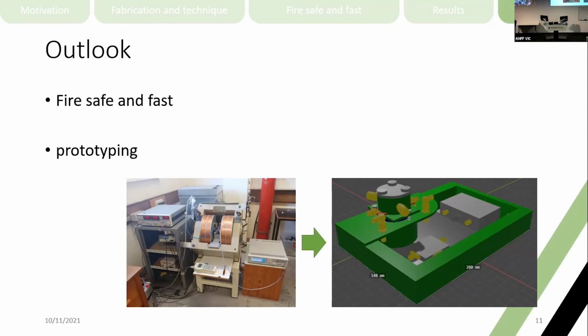Really interesting presentation. And I actually was wondering if you have already tested the hydrogen sensor under a bit more challenging conditions, in air or against potential interfering gases that could give a similar response to what you see for hydrogen. No, we haven't gone too much into that. So we tested our sensor for the response of hydrogen in dry air compared to nitrogen. You don't want to go too high there because it becomes quite dangerous or possibly explosive, of course. Typically, our sensor will respond very similarly in air. We haven't looked into, let's say, poisoning of palladium with hydrogen sulfide or so on. There is research out there which looks at that, but we haven't tested our sensor for that.